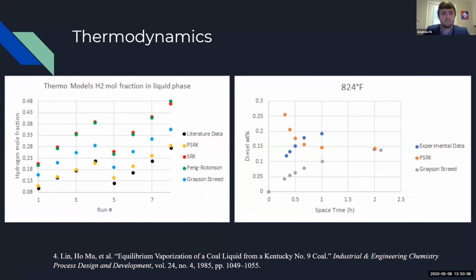To justify our thermodynamics, we added a flash drum after the reactor and measured the hydrogen mole fraction in the liquid phase. And then the literature data is there in the black. And as you can see, PSRK in the yellow is the closest to literature data, fits pretty well, with Grayson Streed not too far behind. But then we decided to go with PSRK because it fit pretty well.